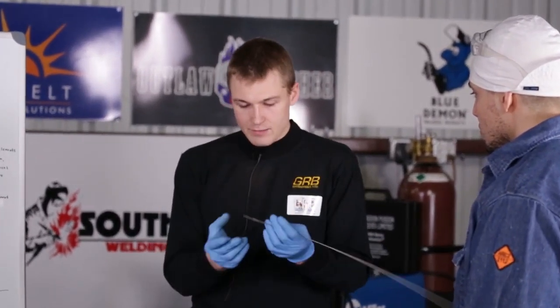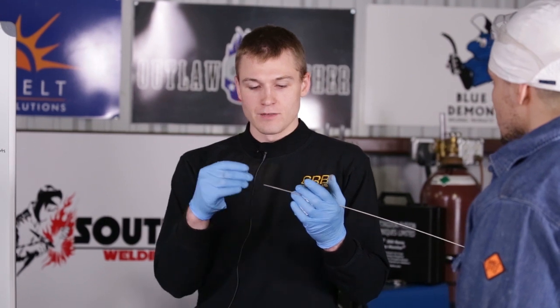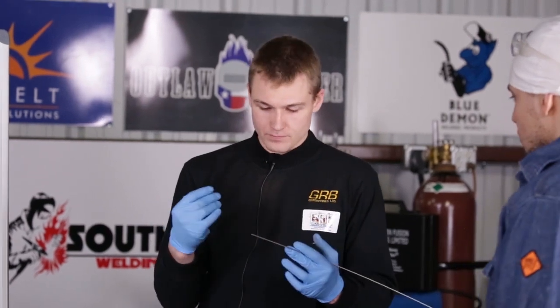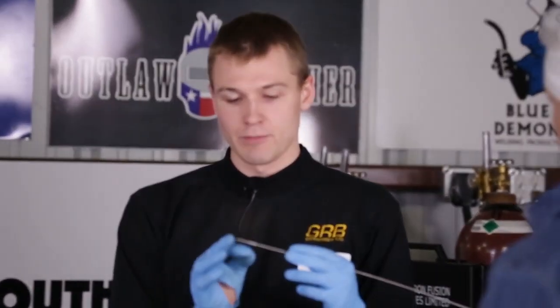And I asked him, how do I weld this metal? How do I close the metal without it trying to stick everywhere? And he told me you need to find a way that the tip of the filler metal does not form an oxide in the first place, because when you form the oxide, it becomes very sticky and now it sticks to everything. So in order to not form the oxide in the first place, you need to have the tip of the filler metal protected within the inert gas of your ceramic cup.